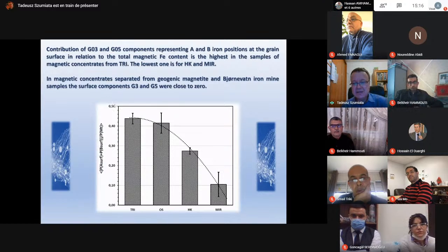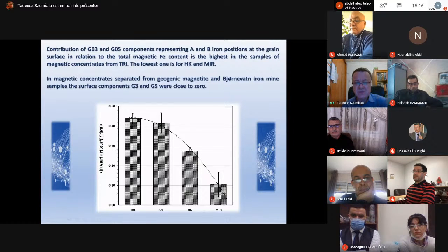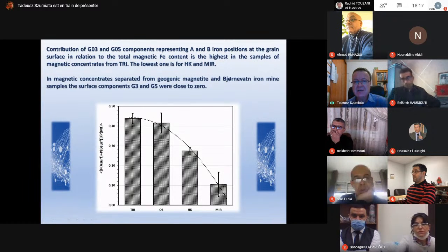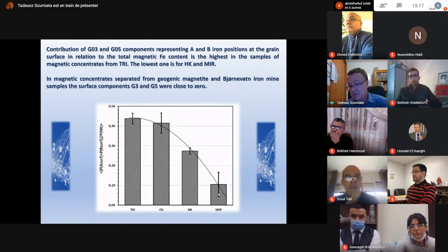It is something new, not visible previously. And I present here a graph where you can see the contribution of these additional components, let's say the surface component. In the case of the sample taken from the Czech Republic, this contribution is over 40% related to the whole amount of magnetite. So this magnetite was very defected, we can say. At the opposite end, we can see this sample from Mo i Rana, this Norwegian sample, more natural, just from a dressing plant of the iron ore. Here this contribution is relatively small, about 10%. And in the case of these strictly natural samples, 2 reference samples, there is no such contribution.